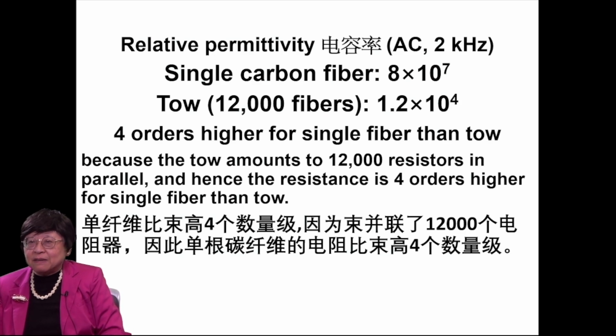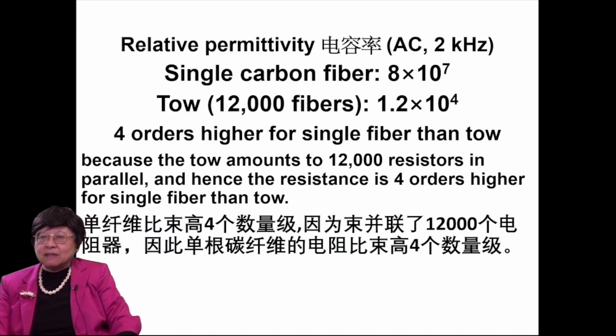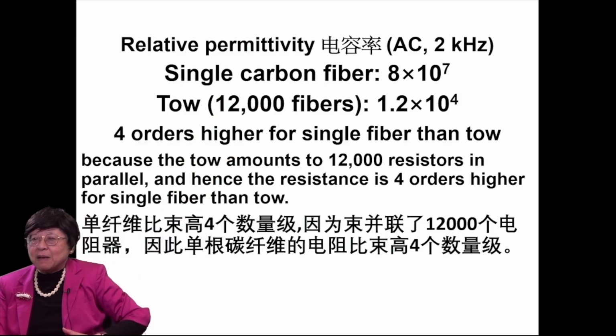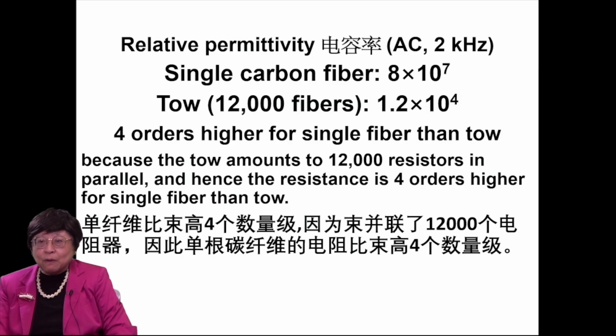The relative permittivity we measure for a single carbon fiber is 8 times 10 to the 7. For a tow with 12,000 fibers, it is 1.2 times 10 to the 4. That is 4 orders higher for the single fiber than the tow. And that's because the tow amounts to 12,000 resistors in parallel, and hence the resistance is 4 orders higher for the single fiber than the tow. A high resistance promotes polarization, and therefore the permittivity becomes higher.